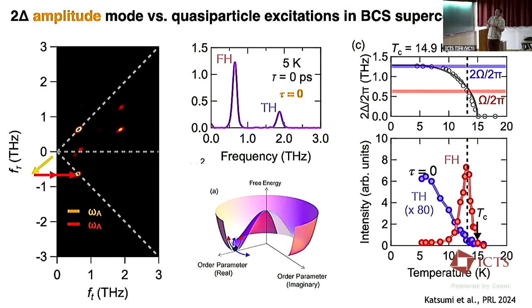superconducting systems like niobium nitride, to look at the collective mode in particular, the so-called amplitude mode, which in some contexts people refer to as the Higgs mode of the superconductor. Famously, in a superconductor, there are at least two collective modes, and one is the phase degrees of freedom, which correspond to the phase winding around the minima here of the so-called Mexican hat potential, but there are also oscillations along the radial direction, and those are the amplitude oscillations. The amplitude mode in a superconductor is a scalar mode. You can't couple to it at the level of linear response theory, but you can couple to it in nonlinear response. And so we've used this in a series of papers, of which one of them is plotted right here